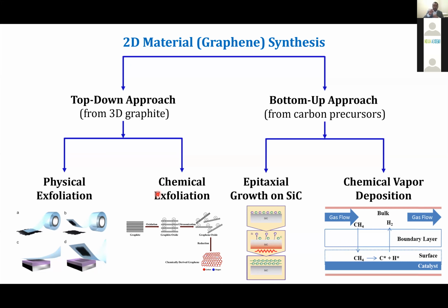When we write in school using a pencil, we produce a lot of graphene layers. Unknowingly, we were actually producing a lot of graphene layers because we're rubbing the graphite on a paper. In graphite, you have a weak van der Waals bond between the layers. So if you use a scotch tape, then you will be able to peel some of the graphene. Of course, there are a few layers of graphene, then you can do multiple transfers on a silicon oxide substrate. Then you will be able to get some one atom thick graphene layers. So this is a simple approach of producing graphene from graphite.